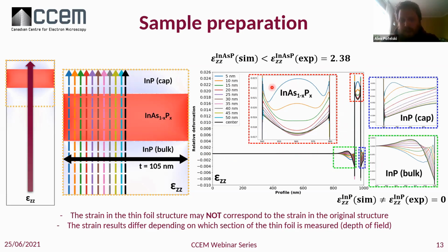If you look at what is happening, the first curves that you have here are near the surface. The curves at the bottom are more towards the middle. And you can see that there is a quite non-negligible variation of strain, depending on where you're looking at the deformation. At the vicinity, here we have the indium phosphide cap and bulk, where we are supposed to have a nice 0, and we can see that there is still some variation. Even in the bulk underneath, some deformation is going negative. If you look towards the surface, some of them are going even positive, then going negative. Some very different types of behavior regarding the deformation.